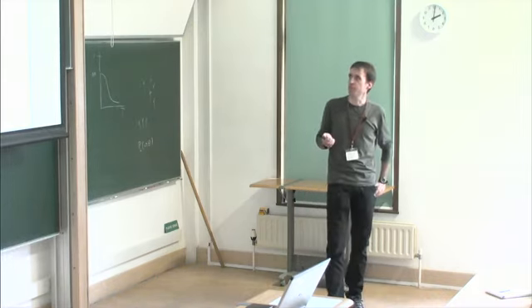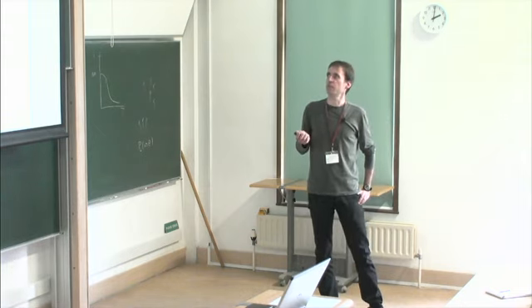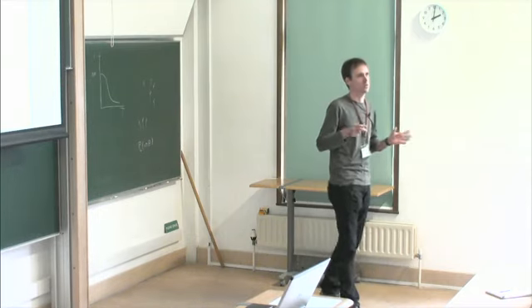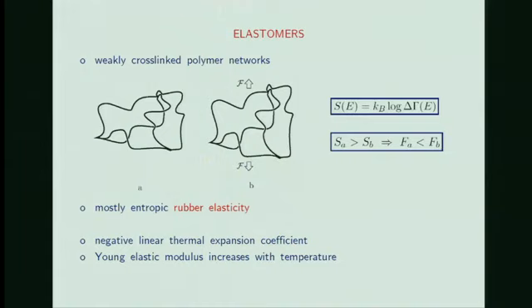resources. The term liquid crystal elastomers is coined from two words, actually three, but two words: elastomers and liquid crystals. Elastomers, as you will know, are typically weakly cross-linked polymer networks, rubbers, with cross-links where the polymer strands meet, and they can explore different pathways in between these cross-links. If you pull on your elastomer, if you stretch it, the number of pathways will be reduced, the entropy will decrease, and you will end up with a restoring elastic force. So you have this so-called mostly entropic rubber elasticity.